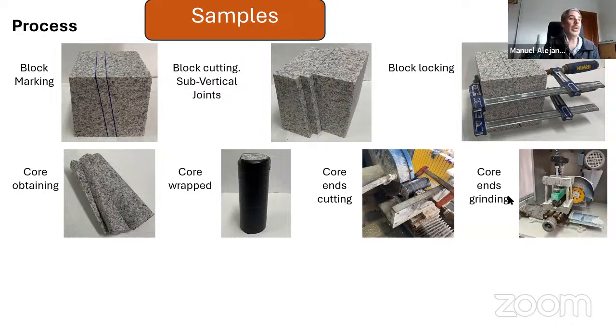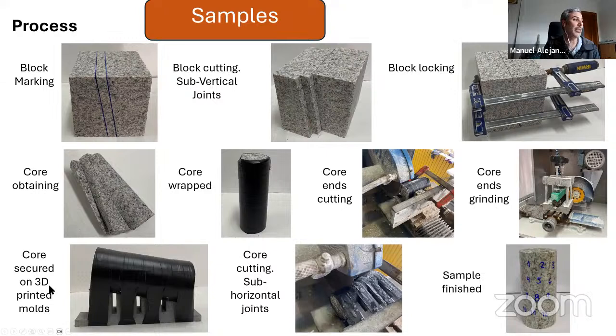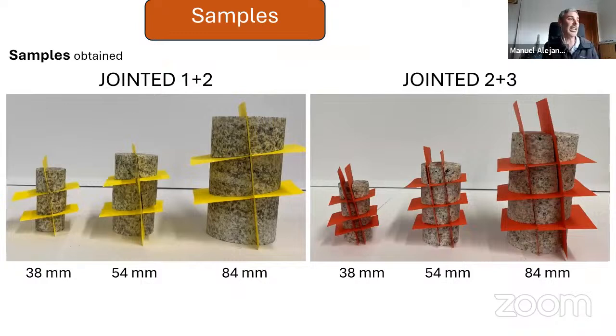We proceed to grind the ends to obtain a smooth surface, and then we secure this sample to a 3D printed mold to give the proper angle to the subhorizontal joints. Then we cut the horizontal joints, and to conclude, we have the samples here in the next slide, and we are going to see the different samples used in this study. We have 38 to 84 millimeters, like in the past study. We don't use the 30 millimeters. And at the left, we are looking at the 1+2 with one subvertical joint and two subhorizontal joints, and the 2+3, that means two subvertical joints and three horizontal joints.